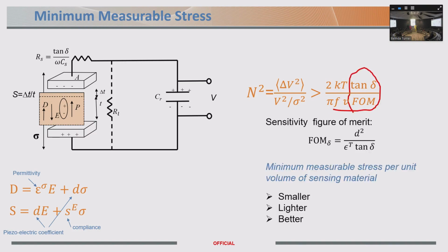And so we get this new figure of merit, which has a new parameter in it, called the dielectric loss, which is the heat generated, or the friction, of the material. And again, this is entirely a material property. So this is the minimum measurable stress per unit volume of sensing material.